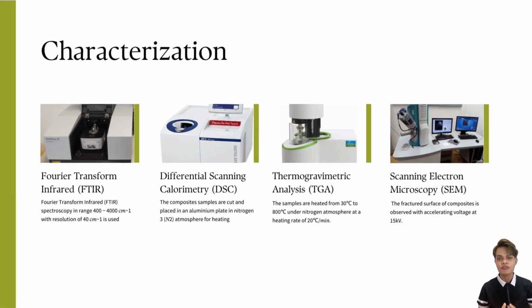The characterization of blended PP and CF is evaluated using FTIR, DSC, and TGA, while the morphology is analyzed via SEM. Fourier transform infrared FTIR spectroscopy in the range 400 to 4000 per centimeter with a resolution of 40 per centimeter is used to determine the change in functional groups of samples. The samples are ground into powder and blended with high purity dried potassium bromide before pressing into ultra-thin transparent pellets.